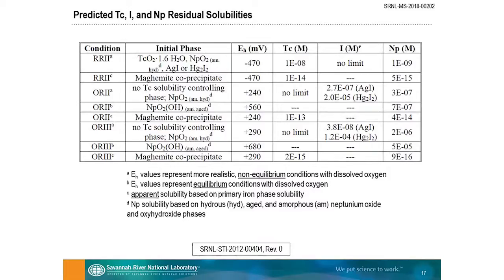Similar table for technetium, iodine, and neptunium. Won't go through all the details, but similar approach as in the three types of samples they looked at. One thing I'll point out is that for iodine, in general, they assumed no limit for iodine solubility. They assumed that it would dissolve. But in the table, you'll also see solubilities for suspected iodine phases, silver iodide, and mercury iodide. And that will be relevant in a minute.